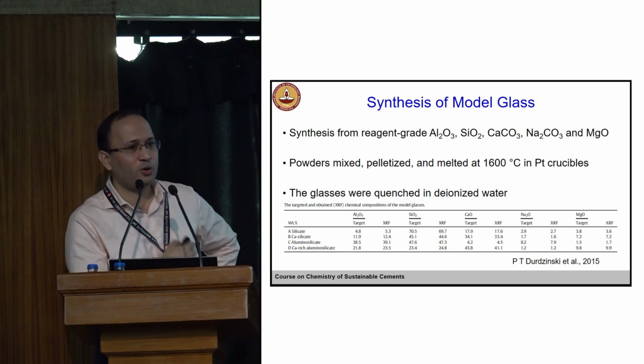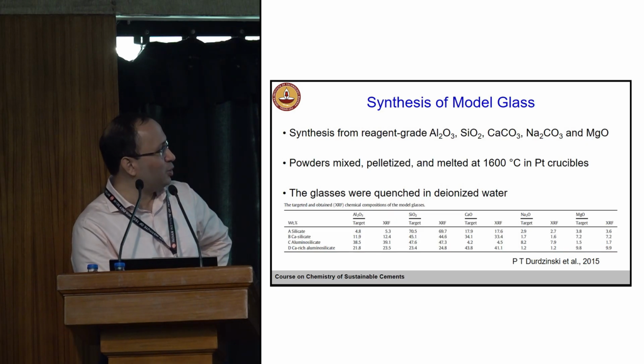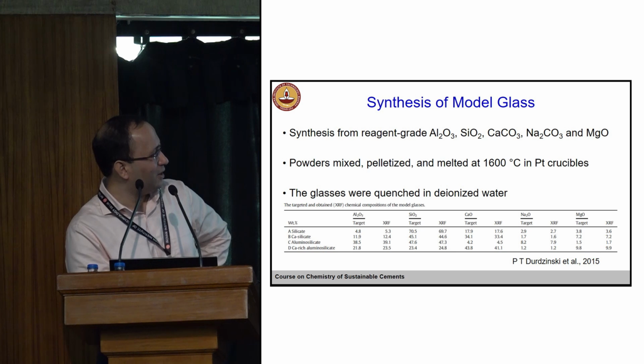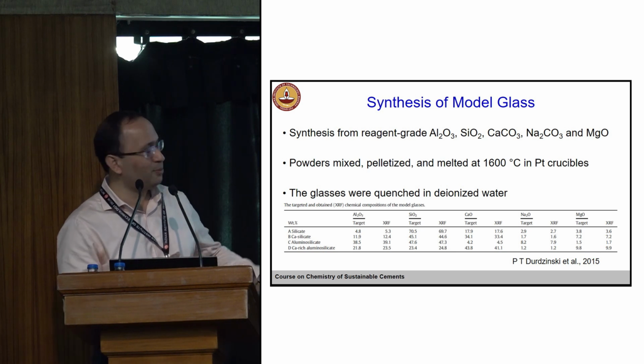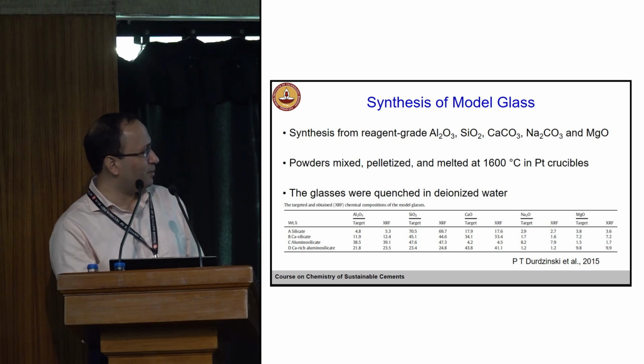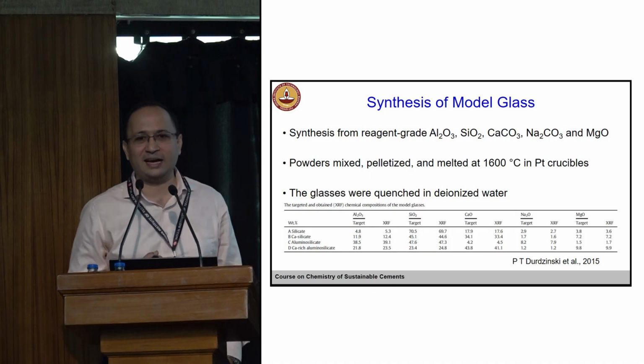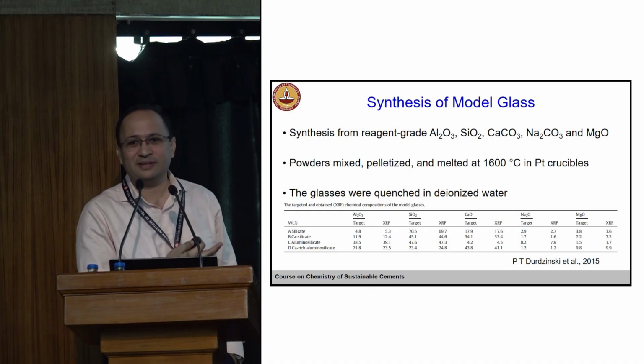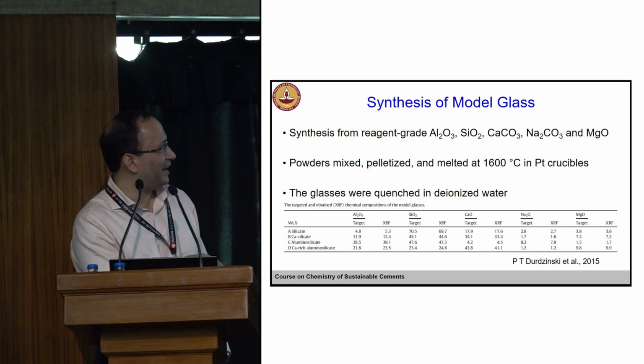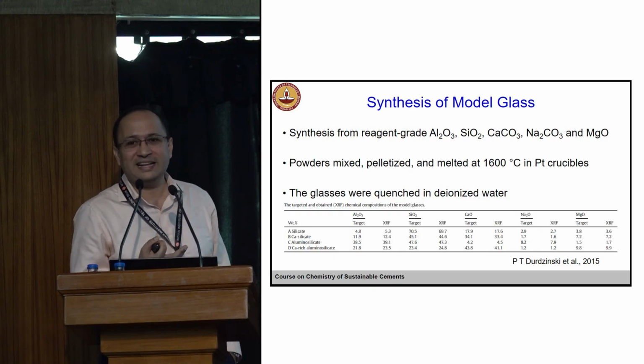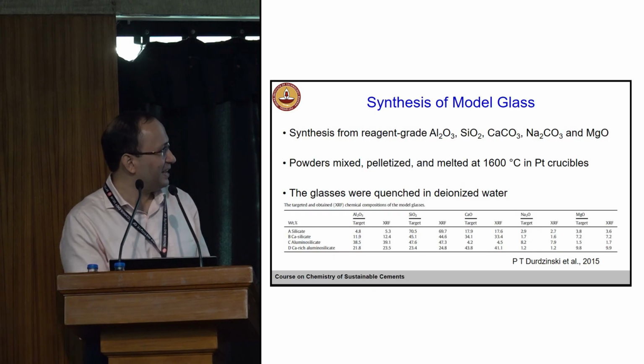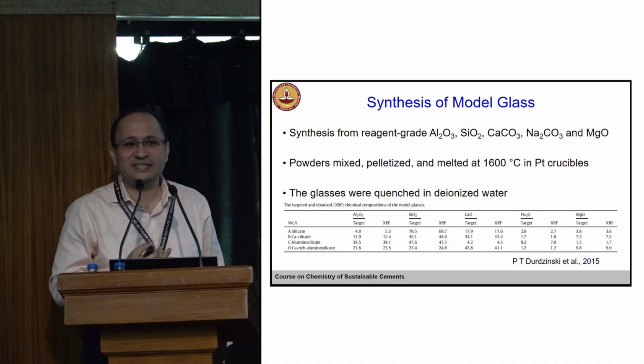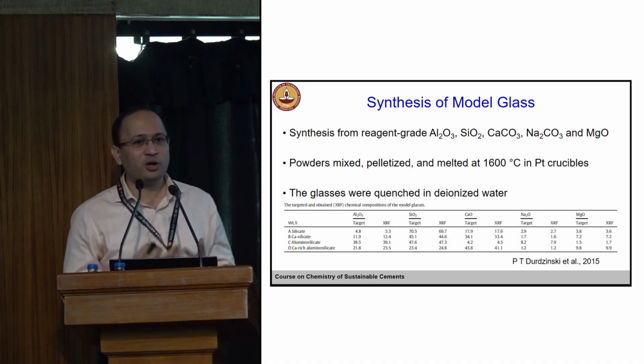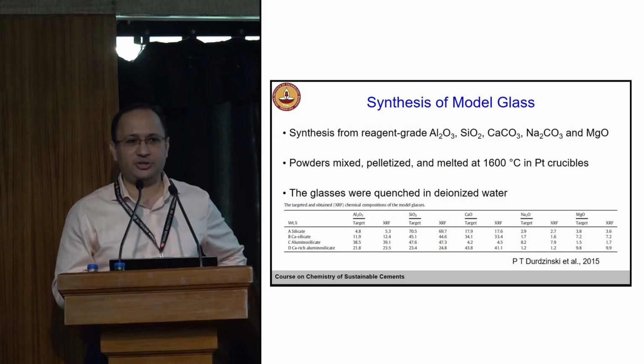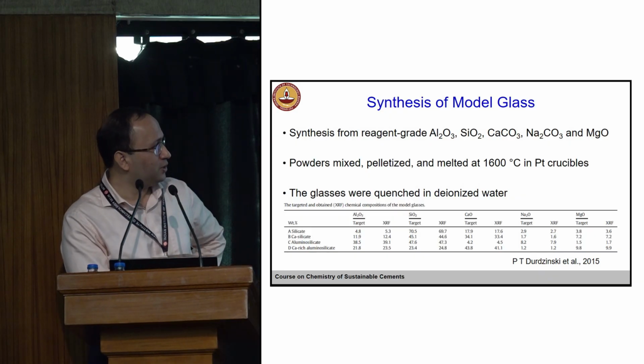Let's say you have some more calcium, then you have aluminosilicate. Now you can see you have calcium-rich aluminosilicate. Calcium-rich aluminosilicate could be like a slag phase. Slag will be similar to this. If you have aluminosilicate, it could be, let's say, calcined clay. Just silicate could be silica fume. So these are model systems where you exactly know the chemistry and composition, and these can be synthesized.